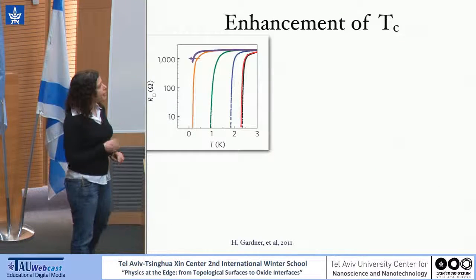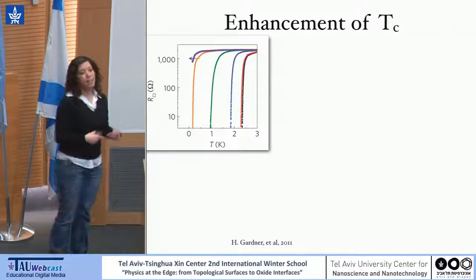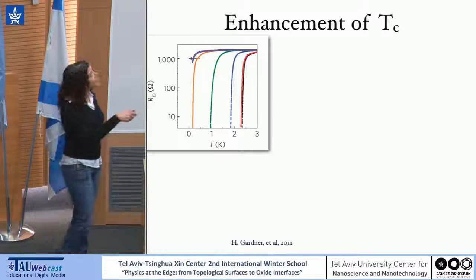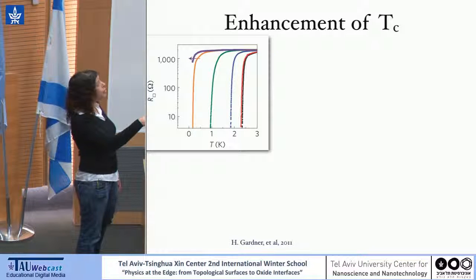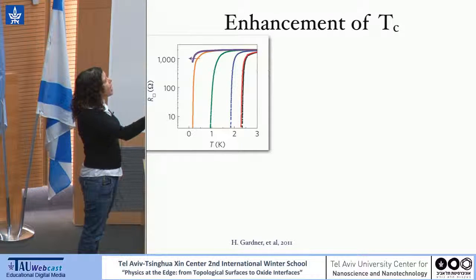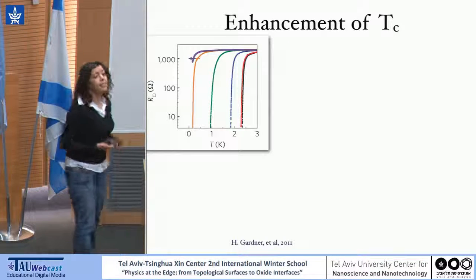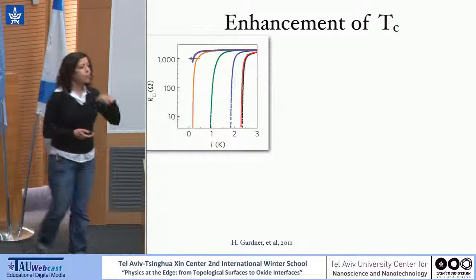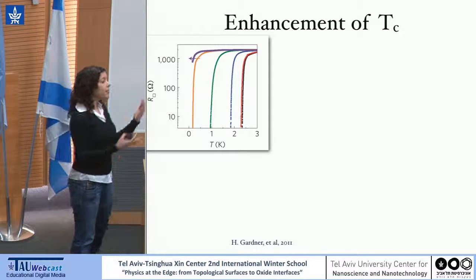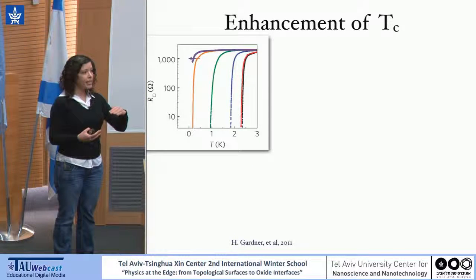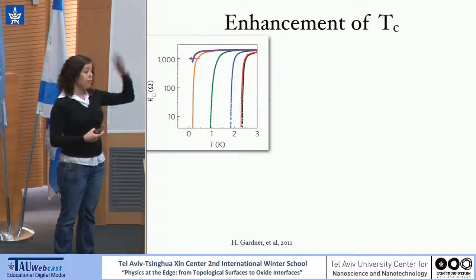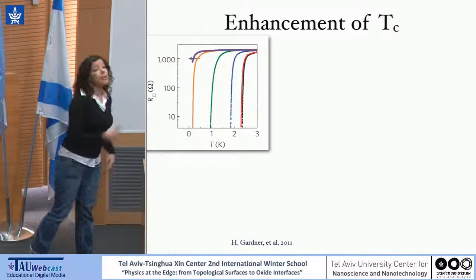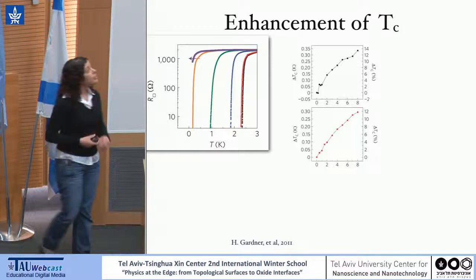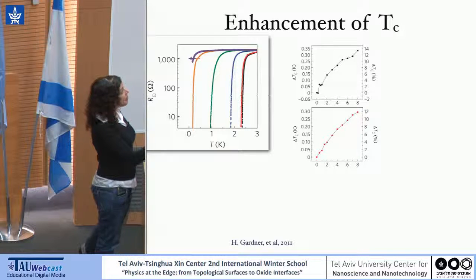So they were checking that. They were actually adding magnetic impurities into the system, and they were checking TC as a function of the doping with magnetic impurities. So basically, as we expect, as the magnetic impurity doping level grows, TC is going down. But what happens now when we apply magnetic field? If this scenario is correct, basically when you apply magnetic field, it will grow further and further the larger the amount of doping is. So here we can see what happened without doping.